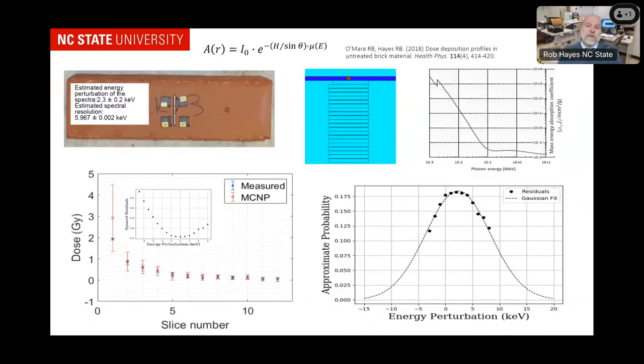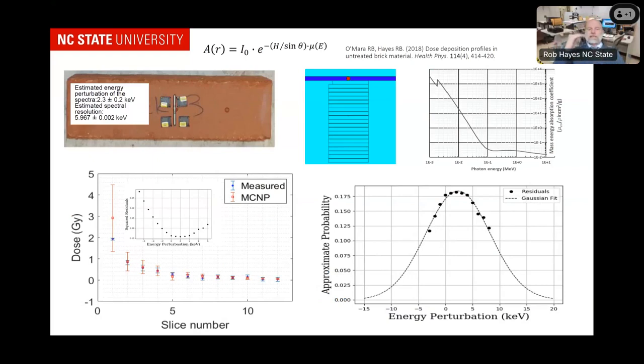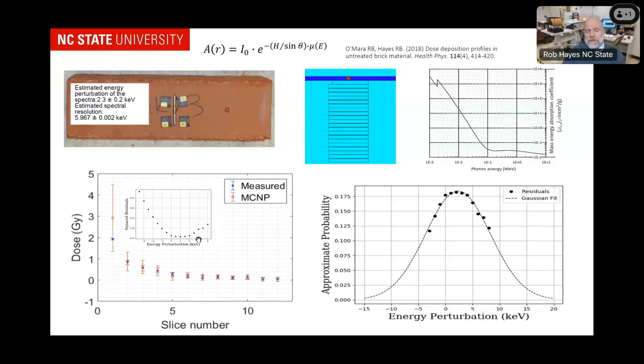Here's another example using americium. I put the americium source on the brick and had a couple of nanodots there for verification and validation purposes. We took a core underneath the brick, sliced it — this is the MCNP schematic showing the slices that were crushed and used for OSL and TL. The mass energy absorption coefficient is energy dependent. Looking at the actual measured dose-depth profile versus MCNP, we get really good agreement. In the inset are the residuals after being perturbed by energy — what would happen if the energy were a little lower or higher — and you can see the sum of squared residuals increases quadratically.